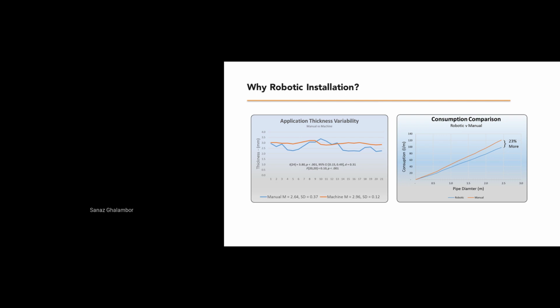Using the robot actually provides true efficiency because of reduced cost of labor and also material. As you see in the graph, the consumption using the robot would be about 23% lower. So it actually has a lower loss factor. We need to consume less material to get the same thickness with the robot than without it. And you can also see that the uniformity of the liner thickness is much better using the robot.